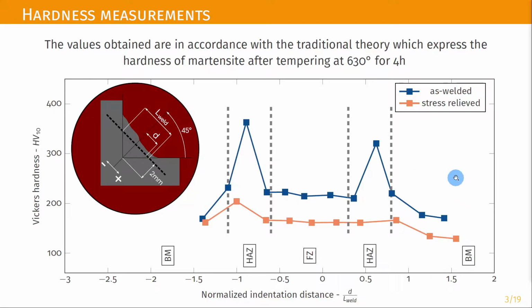In order to study the effect of residual stresses, it was necessary to relieve some specimens. For this reason, a temperature of 630 degrees was maintained for 4 hours with subsequent cooling in the oven. Hardness and microstructure were analyzed to ensure correct treatment.